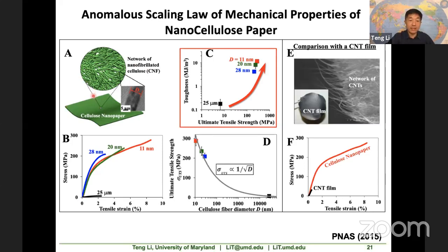First of all, this cellulose nanopaper becomes transparent because the building block has a diameter smaller than the wavelengths of all visible light. More interesting, if you cut a piece of this cellulose nanopaper and do a tensile test, which is shown in plot B here, stress versus strain. The dark curve here corresponds to the regular paper made of 25 micron thick cellulose fibers. You see that it fractures around 2.5% strain and with a very low strength, about single digit to 10 megapascal at most.